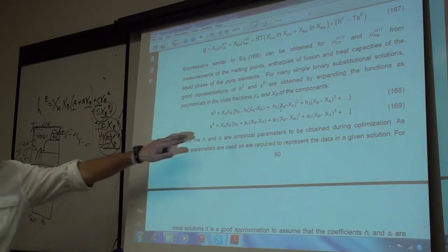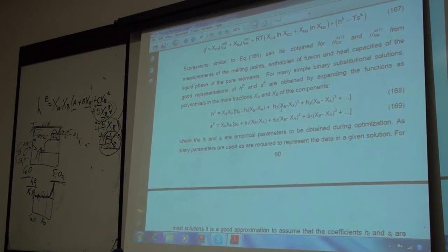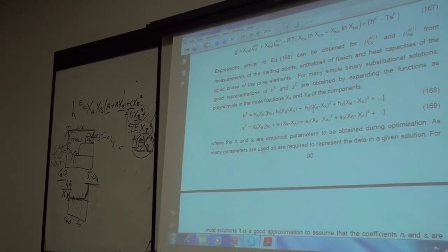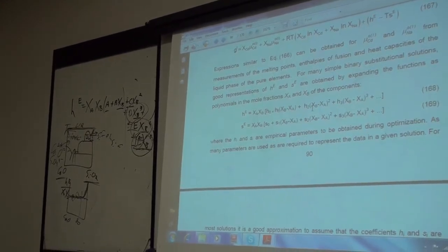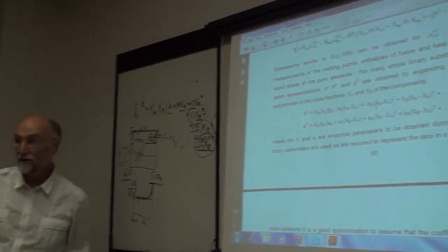And in this model, the entropy terms here are appropriate for vibrational entropy deviating from ideal, but not for the configurational entropy if the deviation is significant, either due to having more than just one particle because the solute dissociates, or due to ordering, long range, short range ordering. In that case, you've got to go to more sophisticated models that change the configurational entropy term as well as just the excess terms here.